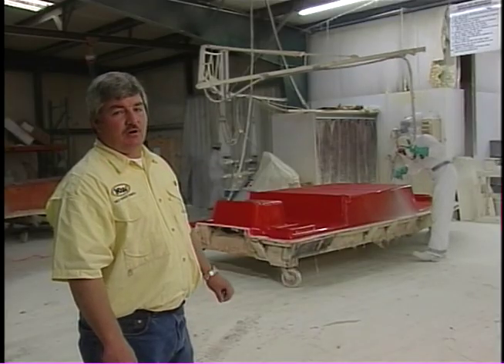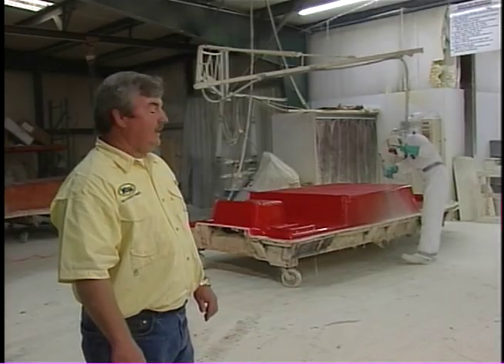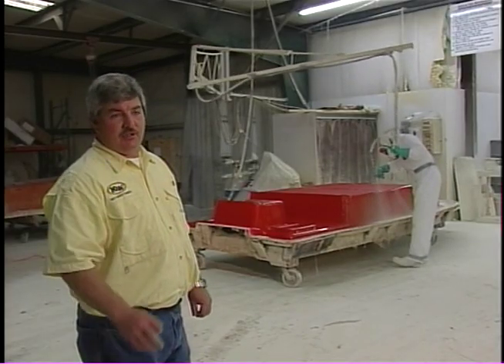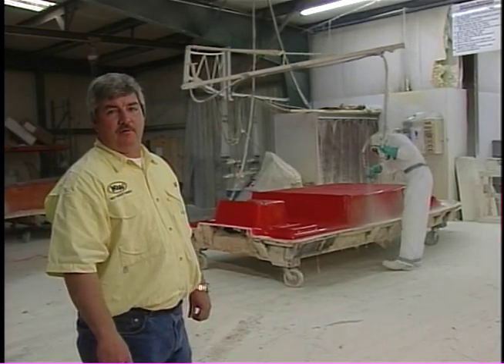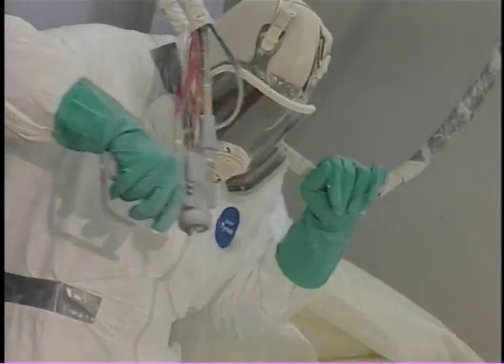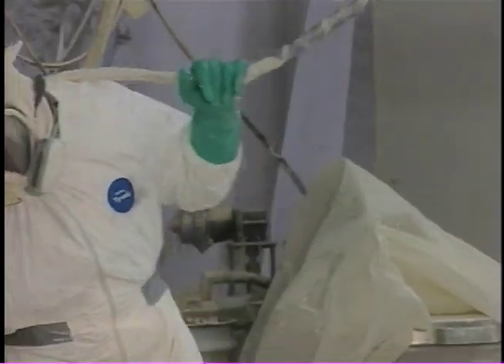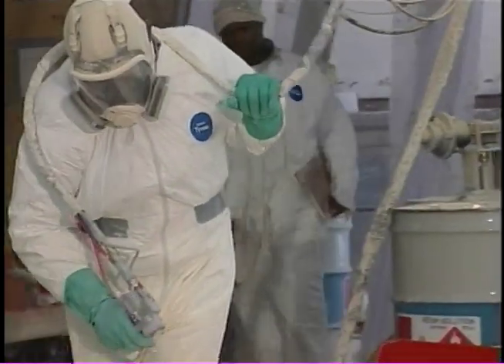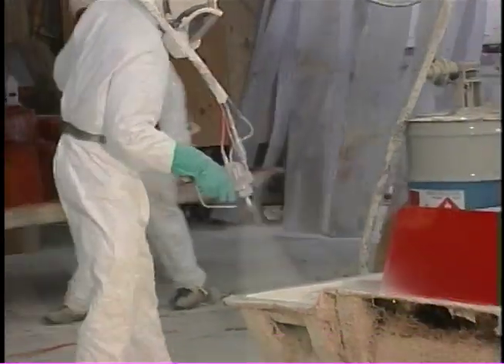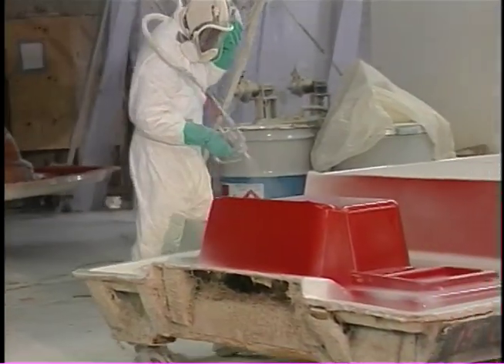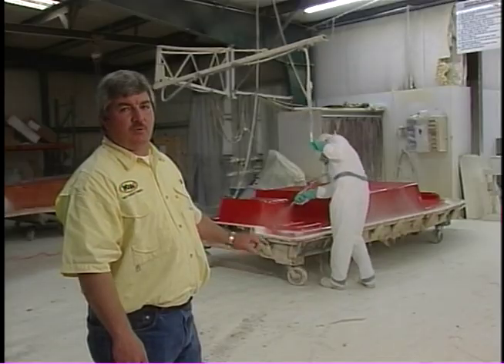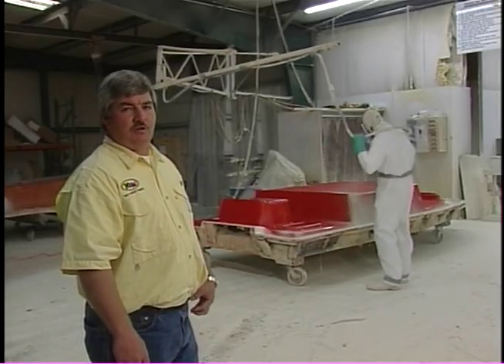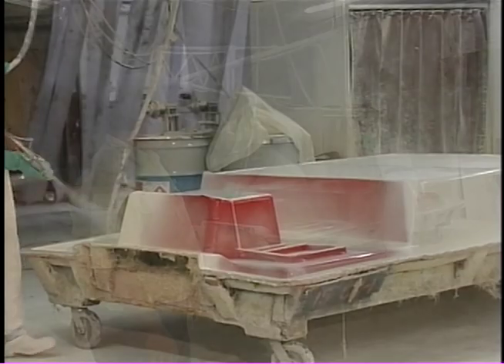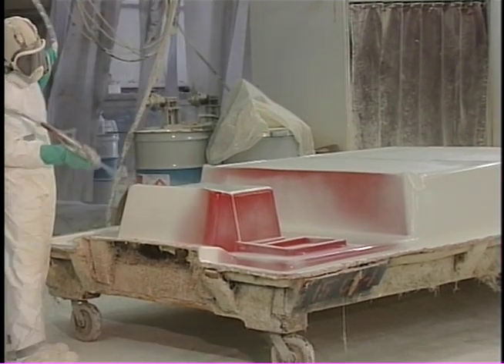And he's putting this gel coat on, and he's got to apply it at the exact right mil thickness to make sure that we'll get the proper weathering of the boat. If you're too thin, you'll get alligatoring, the gel coat will wear out, and you won't have the waterproofing. If you get it too thick, you'll have stress cracking and problems with weathering later too. So this is the most important step, to make sure that the gel coat is put on at the right thickness. This is inside out and backwards. You have to think inside out and backwards.